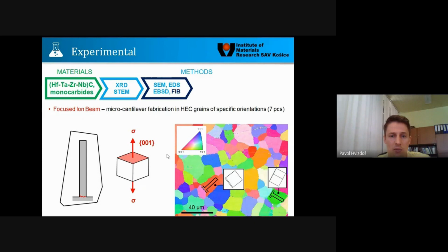For example, we prepared micro cantilevers. As you can see on the left side, we selected grains because we were focusing on only the mechanical behavior of the grains. So we selected large grains from which we fabricated the cantilevers. I mean, cantilevers from the top were entirely in the grain. Unfortunately, in the bottom, I mean, in depth, we had problems in some cases because we never knew how deep the grain was that we selected for the fabrication. But of course, those tests which turned out to contain several grains, not only one, were excluded from the data analysis. So all in all, we fabricated 7 cantilevers from 2 different crystallographic orientations from the top